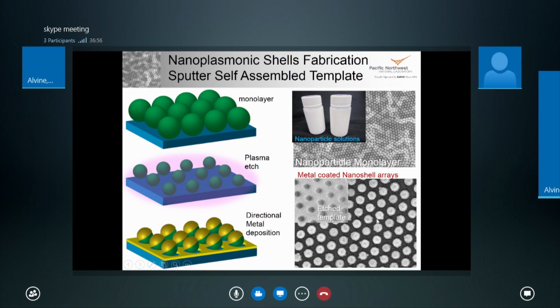These are all the nanoshells. The reason we do the plasma etch is because if we didn't etch them, when we deposited the metal we would get a rough metal surface, and that doesn't have the plasmonic properties. So to create the discrete shells, but also keep them as densely packed as we need, we have to do a plasma etch for that.